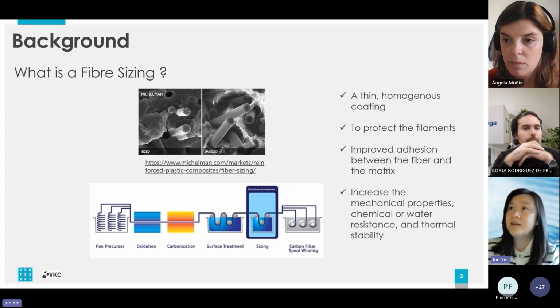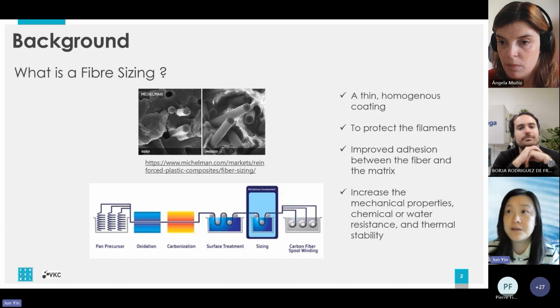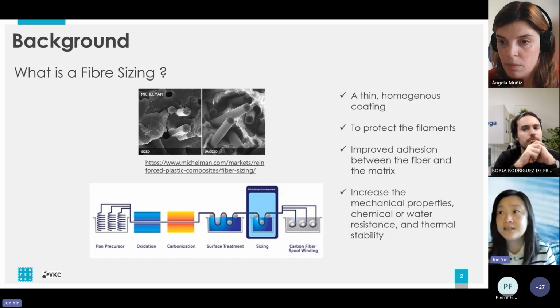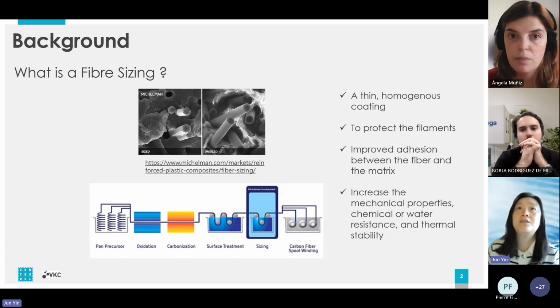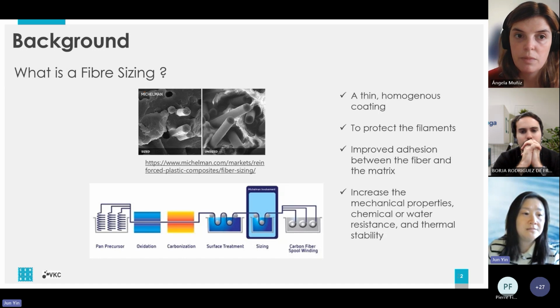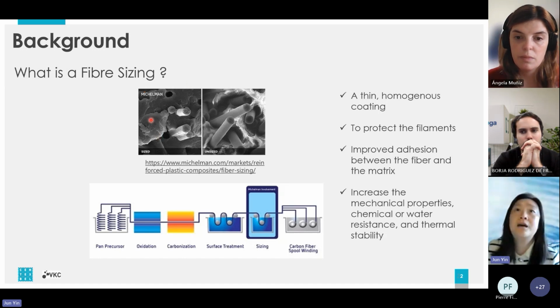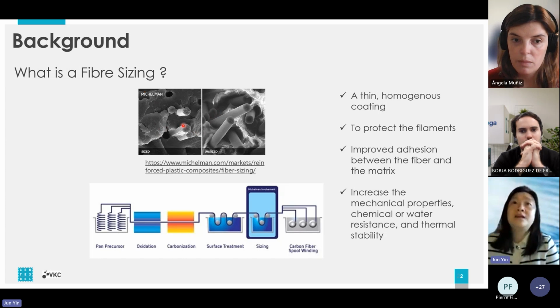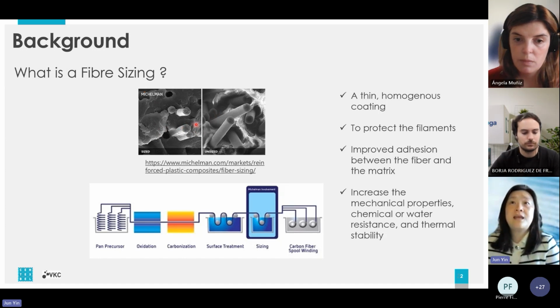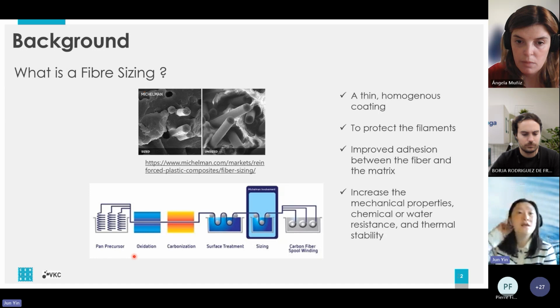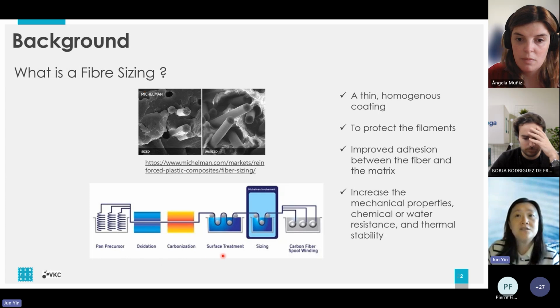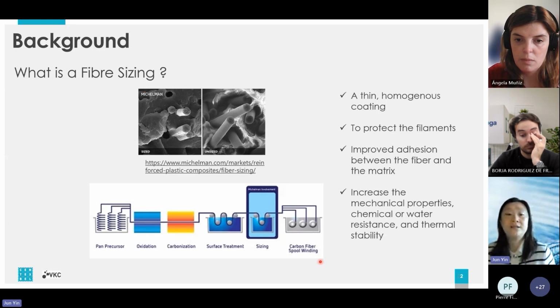So in the composite, it can improve adhesion between the fibers and the matrix, and also it can increase the mechanical properties, chemical or water resistance, and the thermal stabilities. So if you look at this photo here for the sizing from Michelman, you can see the difference between sized carbon fibers and unsized carbon fibers. During carbon fiber manufacturing, there's the PAN precursor, oxidation, carbonization, surface treatment, the process of sizing, then carbon fiber spool winding.